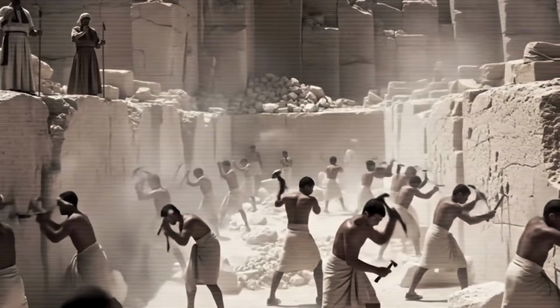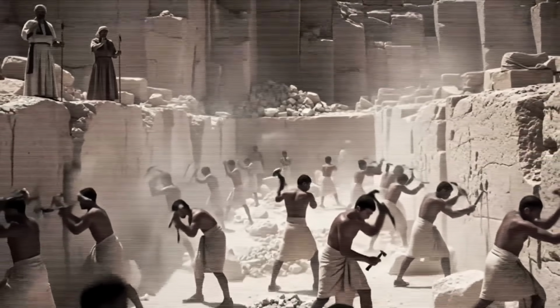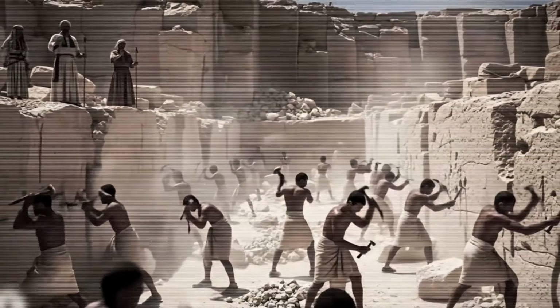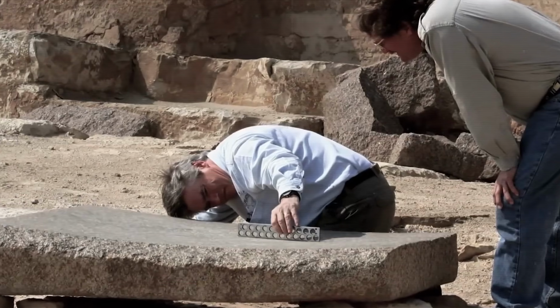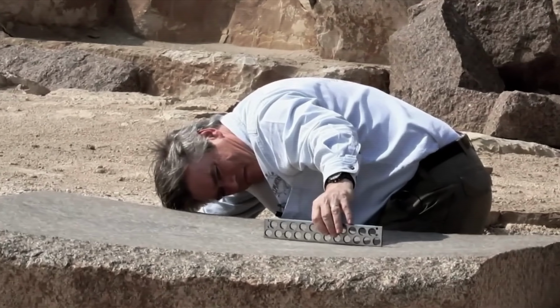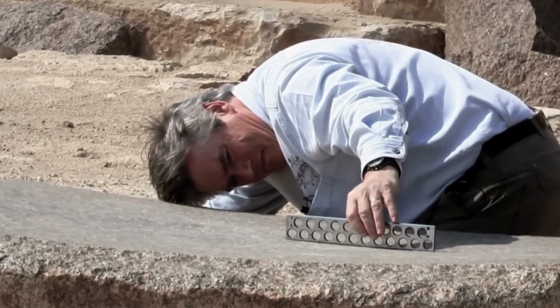Denys Stocks, an experimental archaeologist at the University of Manchester, spent years testing this. He built accurate replicas of the copper tube drills and flat copper saws that the mainstream account credits. He sourced appropriate sand. He applied what the evidence suggested about ancient technique as faithfully as he could. His published results showed that copper tube drills with quartz sand could drill granite, but at a rate of advancement measured in millimeters per hour with rapid copper degradation that required continuous tool replacement. The surfaces produced were rough, inconsistent, and bore no resemblance to the clean, continuous spiral grooves that Petrie had documented.